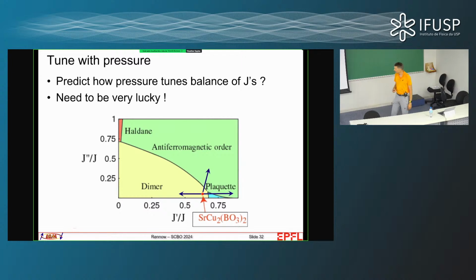And one of the things you can do, if you want to change a material, as I mentioned, we were not able to find another material that has the same model. In fact, this particular material doesn't even want to be chemically doped. Anything you try, you put calcium instead of strontium, it doesn't work. So basically, you can't do much. But one really beautiful tool we have available for condensed matter systems is pressure, which changes the crystal structure, and that will change the ratio of couplings in the system. The only thing is that it's really hard to predict how it changes. So it could be we're going this way, this way, and only if it goes this way, when we apply pressure, would we be lucky enough to get some new physics.